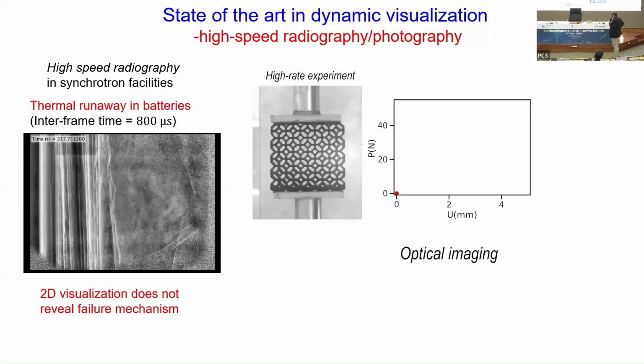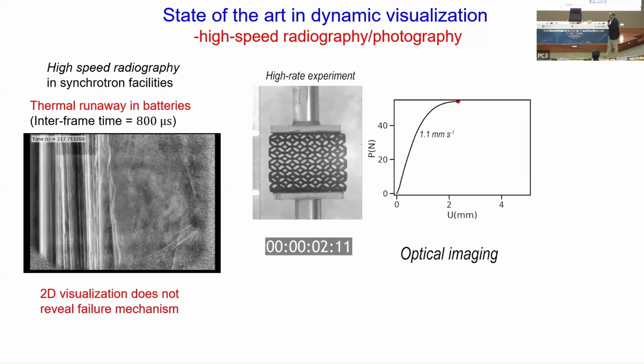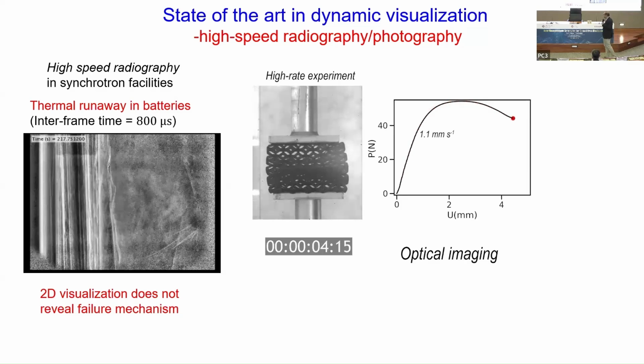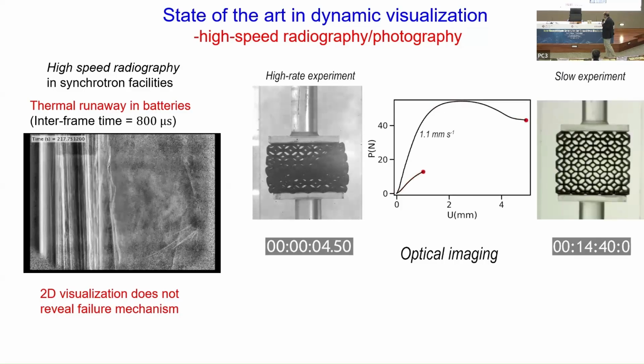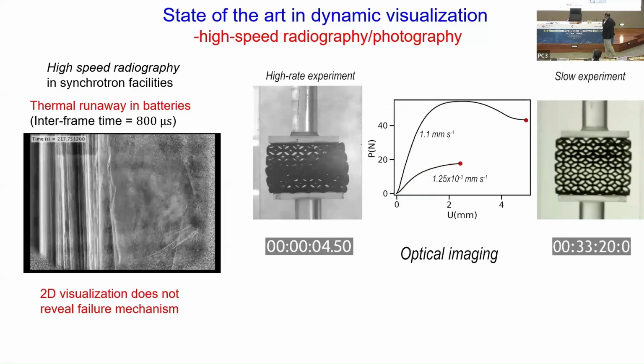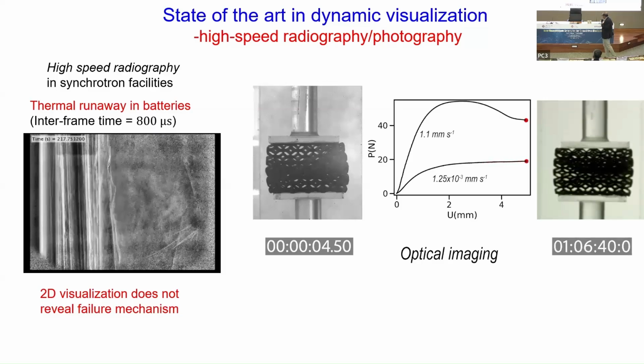Now, what else can you do? Suppose we do a lab experiment. This is high-speed photography. You compress this at a reasonably high rate. This experiment is finished in 4 seconds. Well, it was a softening curve. A much slower experiment, which went on for nearly 1 hour, had no softening.